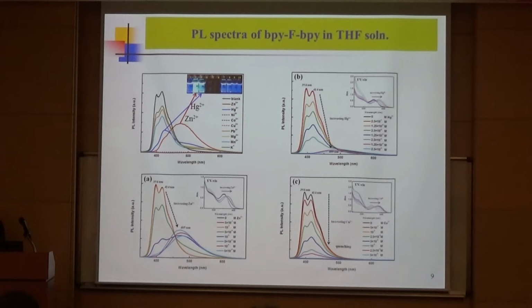For zinc ion titration, with increasing ion concentration, we first observe partial fluorescent quenching without spectral shift at a low ion concentration, and then further fluorescent quenching with an additional band showing up at a moderate ion concentration. Finally, the emission peak completely shifts to this additional band at high ion concentration. For the mercury ion titration, we observe a similar fluorescence response, except the additional band shows up at a much higher ion concentration. For the copper ion titration, we just observe fluorescent quenching without spectral shift with increasing ion concentration.